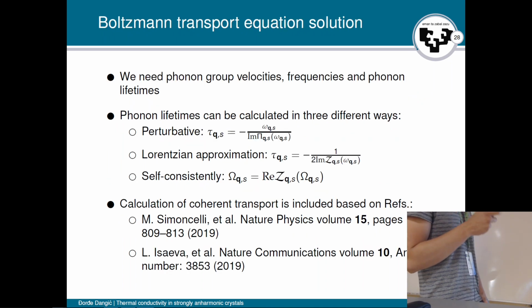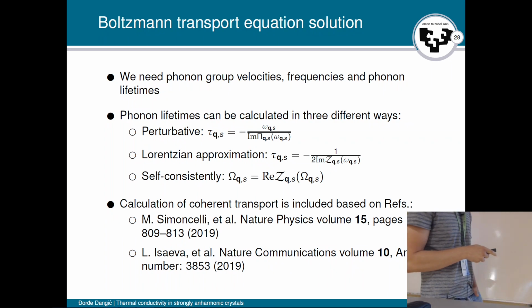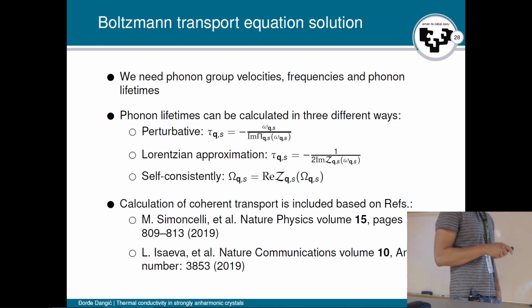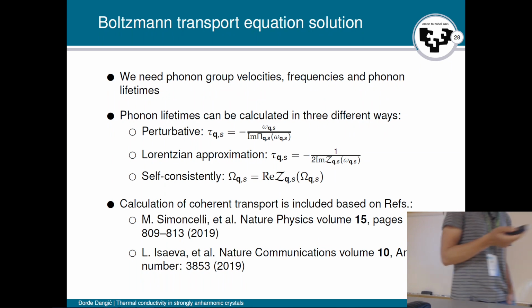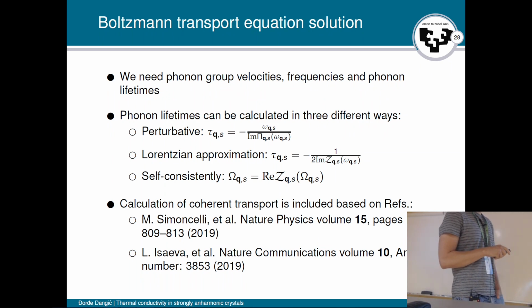Okay, so to do the Boltzmann transport equation solution, what we need are phonon group velocities, phonon frequencies, and phonon lifetimes. And the phonon lifetimes, as has been discussed by Raffaello in previous days, can be calculated in 3 different ways. Well, he was talking about the phonon linewidth, which is basically just the inverse phonon lifetime. The first way is the perturbative one, which is identical to all the other codes that calculate lattice thermal conductivity, where we have the imaginary part of the self-energy inversely proportional to the phonon lifetimes. So this is the perturbative part.